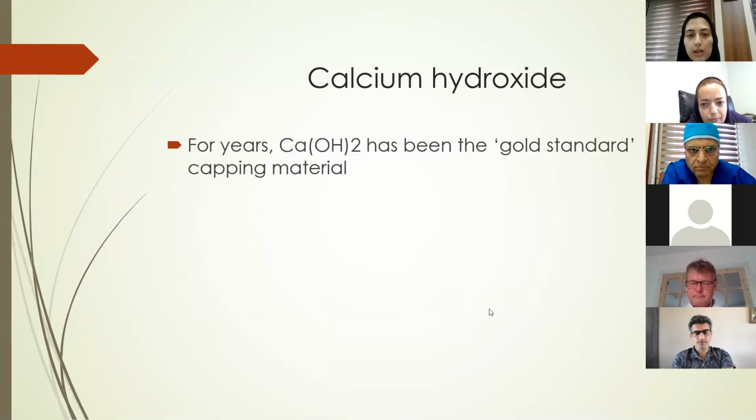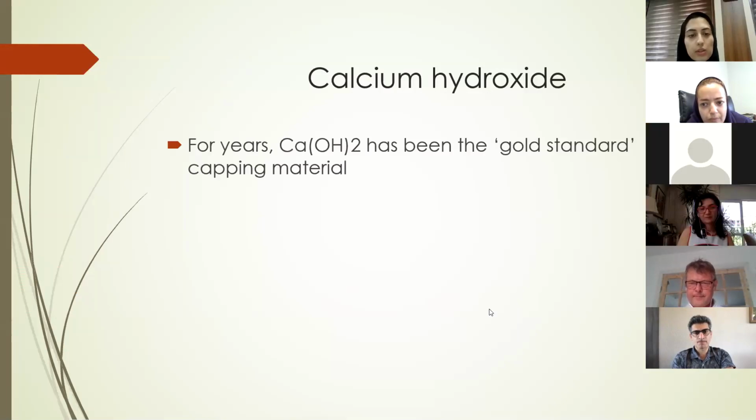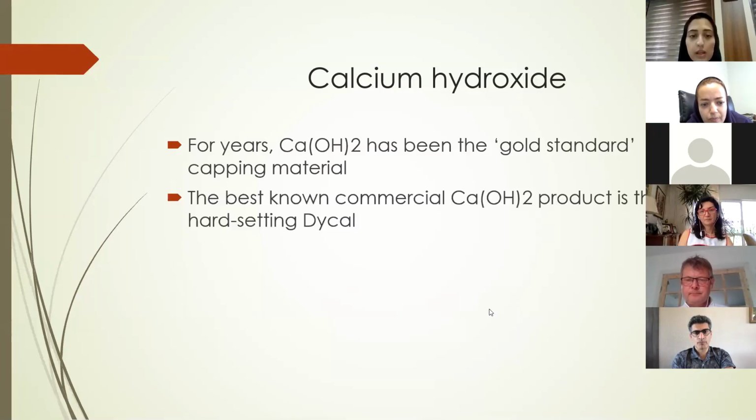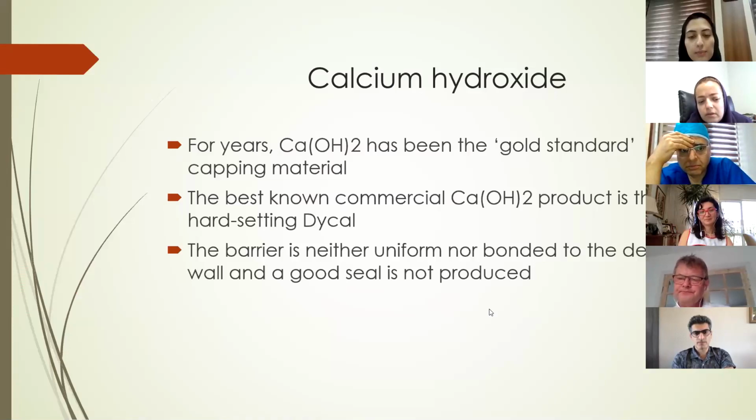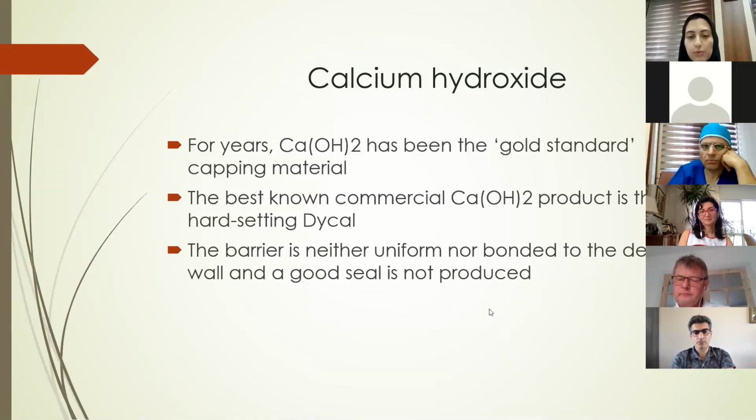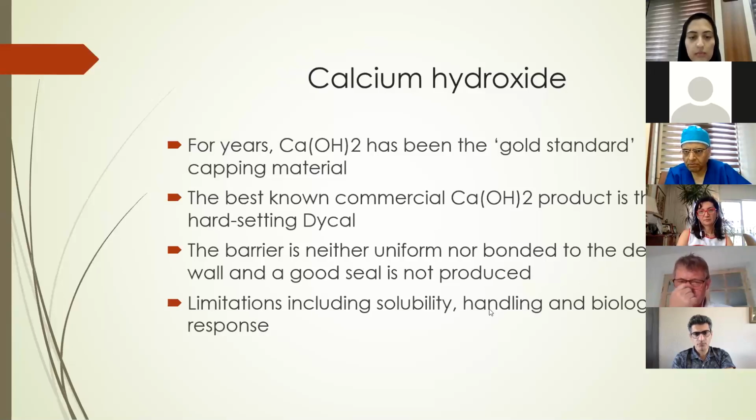About calcium hydroxide, it has been the gold standard capping material for years, and the best known commercial form of it is hard-setting Dycal. But the barrier which is provided by using this material is not uniform histologically, and it does not bond to the dentine wall, and it does not provide a good seal. Other limitations include solubility of this material, and also the handling is not favorable, and the biological response is questionable to this material.